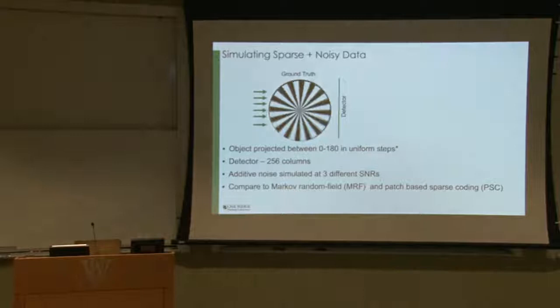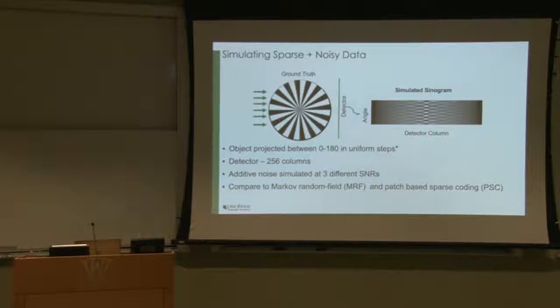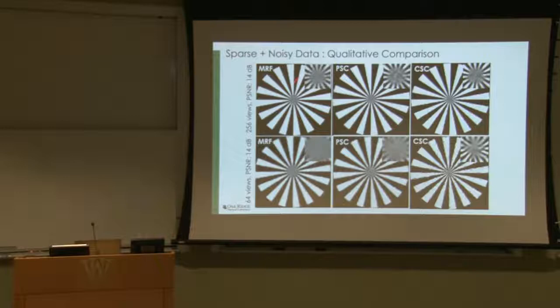I simulated noisy CT data and reconstructed it using the techniques we saw in part one, which use simple sparsity-based regularizers. And this is using another technique called patch-based sparse coding. And this is the convolutional sparse coding with the plug-and-play approach. So at the center of the spokes, you can see that the resolution can be significantly improved by using better regularizers than just pure sparsity, especially when you have noisy data. So it shows that model-based techniques can be improved further by the design of good image models. So if you have a model for your signal, this, of course, makes sense, but then how do you do it was what this part of the talk was about.